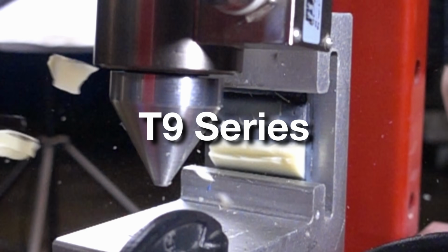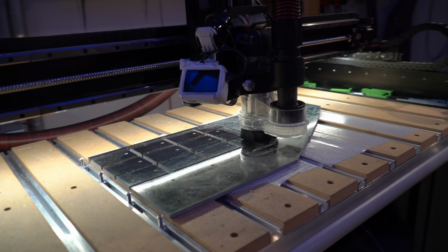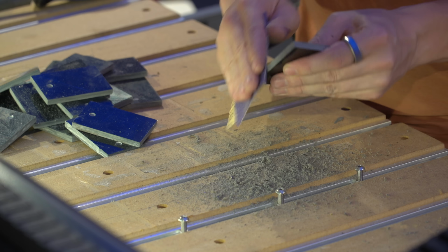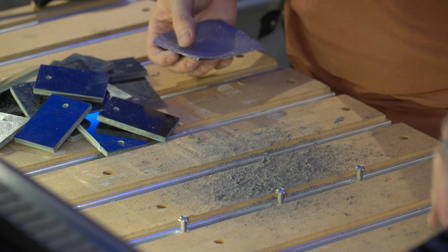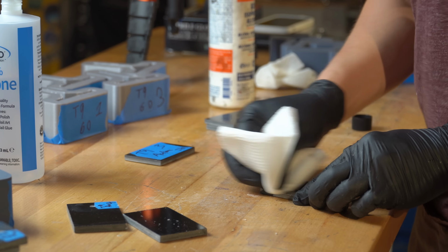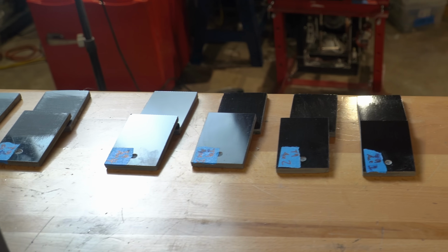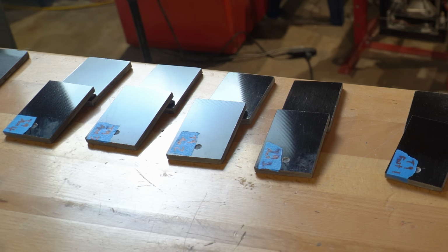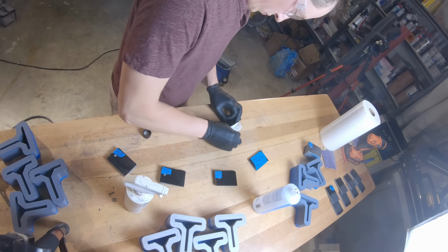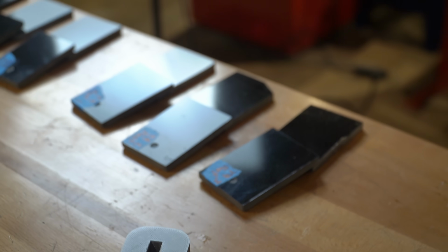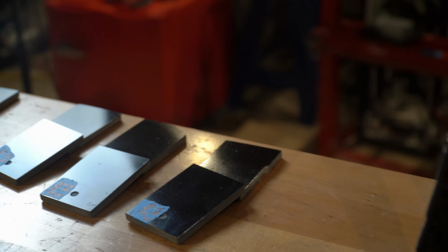I cut out a new series of test coupons, and we're going to run 11 tests. First, we're going to do 4 coupons that are straight up what the expert said. No sanding, just 10 seconds of wiping with acetone, and cleaning it after with IPA. I'm using regular paper towels for acetone, and the IPA is done with a lint-free wipe to reduce debris. Technically, you should do lint-free for everything, but this is a YouTube video, not a research lab.